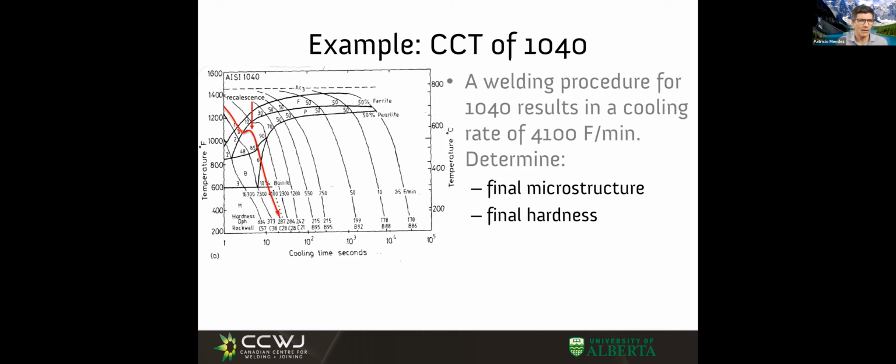So at this point here, we have a bunch of untransformed. What do we have? We have, let's say, 91% austenite that has not transformed. 91%. 8% primary ferrite, and let's say 1% pearlite. All right, keep going down. What do I get now? What is my microstructure right here, just before crossing the line? What do I have there?